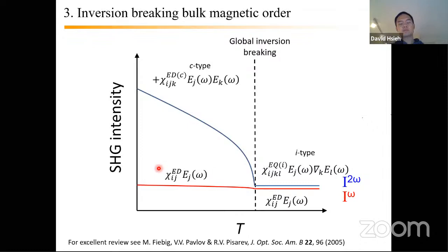One of the more striking examples of what can happen is if your sample breaks inversion symmetry due to magnetic ordering. So here, for example, you might again start at high temperatures with some higher multipole bulk response of I type, but if your magnetic order breaks the inversion symmetry of the underlying crystallographic structure, then you can have a C-type electric dipole radiation term turn on, which usually is very, very strong. And that starts to dominate your signal. And again, these are not so easily borne out in linear optics measurements.